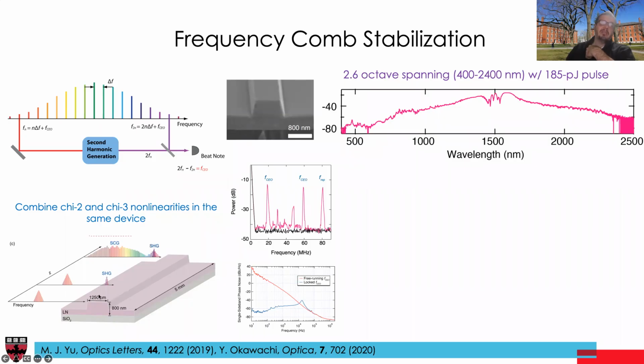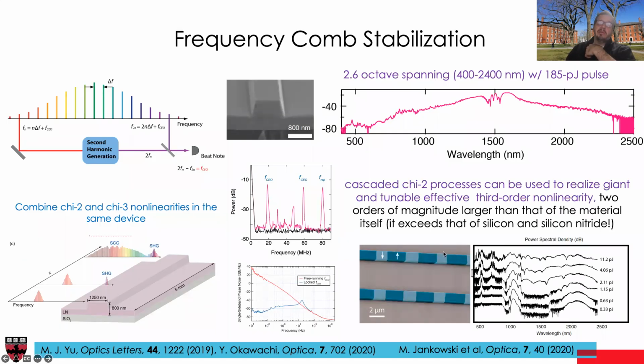However, the nice thing about lithium niobate is that the nonlinearity of this waveguide can be engineered. And this can be done by periodic poling. It's some work we've been doing with Martin Fejer, and I'm not going to go into details here, but basically what we can show is that by periodically poling lithium niobate, we can increase the effective third order nonlinearity of lithium niobate by 2 orders of magnitude, essentially, compared to the material's intrinsic third order nonlinearity,